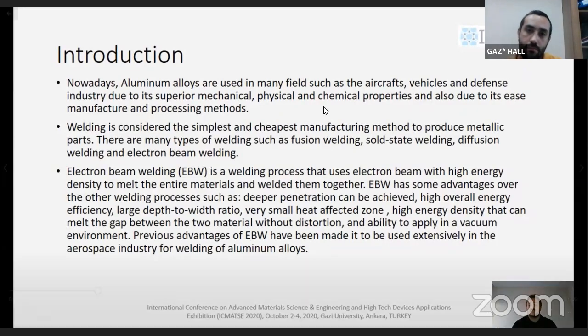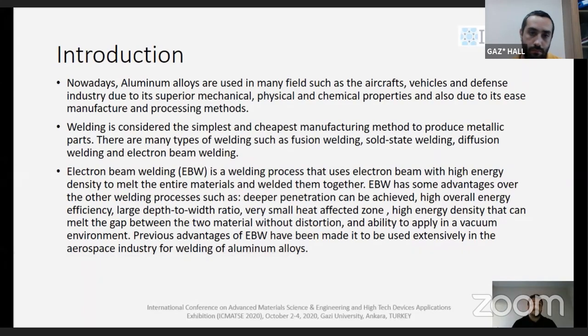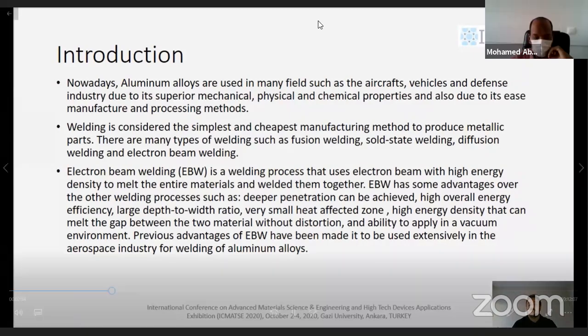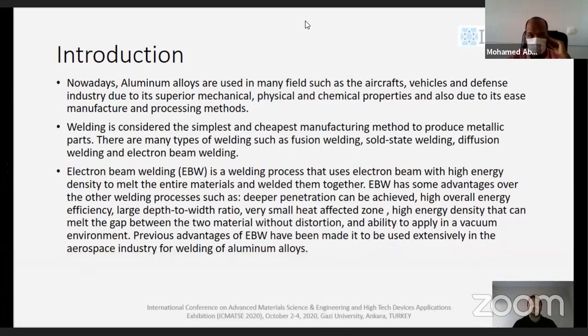Electron beam welding has some advantages over the other welding processes, such as deeper penetration, high overall energy efficiency, large depth to width ratio, very small heat affected zone, high energy density that can melt the gap between the two materials without distortion, and the ability to apply in a vacuum environment. Previous advances of electron beam welding have been made to be useful extensively in the aerospace industry for welding of aluminum alloys.